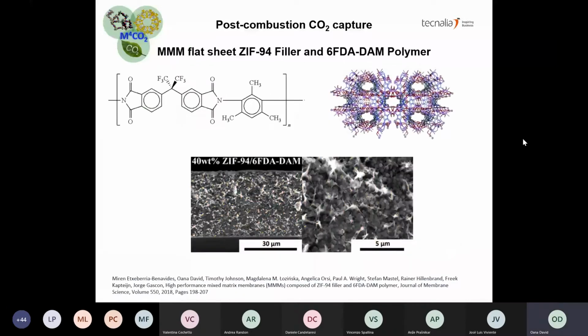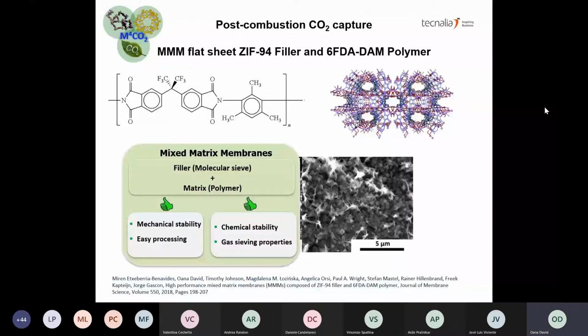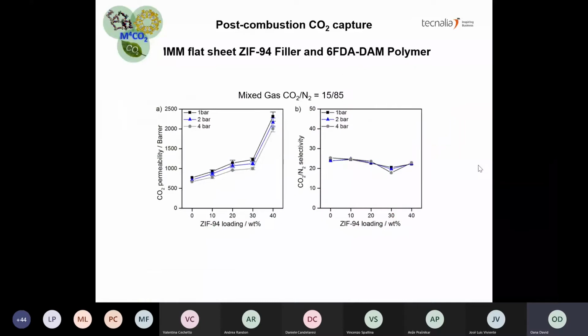And then with the 6FDA-DAM, the polymer I showed you that was much more permeable, we try to increase the selectivity for this separation by incorporating an inorganic filler that can sieve between carbon dioxide and nitrogen. And this was ZIF-94. It's a metal organic framework. So that could give good sieving properties. And here on the SEM picture on the right side, you can see the particles, which are nano size, embedded inside the polymeric matrix. And with this experiment, we managed to increase carbon dioxide permeability a lot, but the selectivity was maintained constant. So we didn't manage to also increase the selectivity.